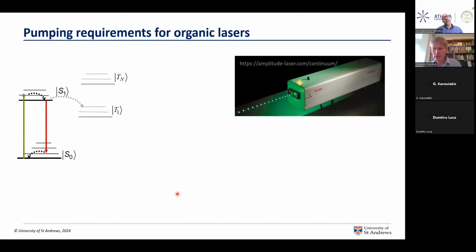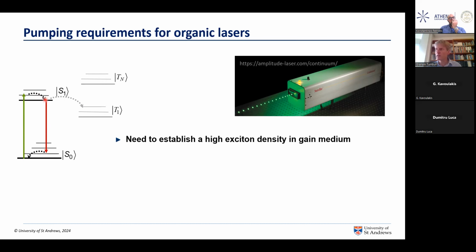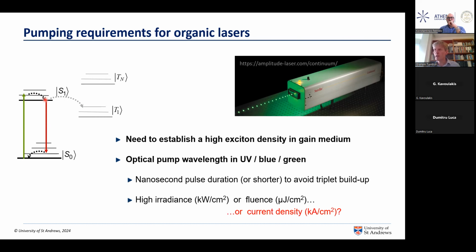So in order to drive our organic lasers, we need to think about how we pump them, how we create this exciton population in the upper laser level. And so what we need to do is establish a high density of exciton excitations in the gain medium. If we are optically pumping, then typically we need to use a laser emitting ultraviolet, blue, or green light, usually with nanosecond pulse durations or shorter, because we need to establish the population inversion before fluorescence depletes the upper laser level, but also to try to make the laser switch on before the triplets build up and start to add losses to the gain medium.